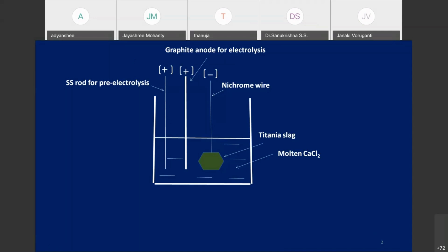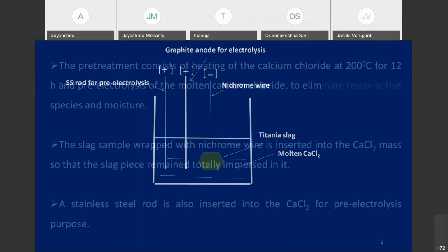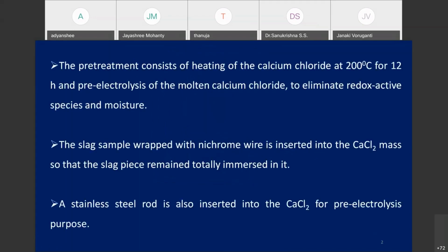I'm briefly describing this part. Okay, the pre-treatment consists of heating at 200 degrees Celsius for 12 hours. Then you carry out the pre-electrolysis of molten calcium chloride to eliminate any redox active species or moisture.